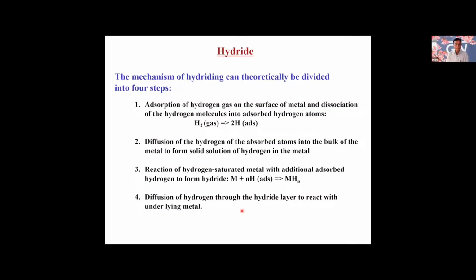So here are the different mechanisms which one has to be familiar with, of hydriding. So adsorption of hydrogen gas on the surface of metals and dissociation of the hydrogen molecules into adsorbed atoms. So when you have a gas, when it absorbs, then you have atomic hydrogen. Then diffusion of hydrogen and adsorbed atoms into the bulk of the metals to form solid solution of hydrogen. If it is more, then it becomes a hydride. Then diffusion of hydrogen through the hydride layers to react with the underlying metal. So these are the different mechanisms for hydriding.